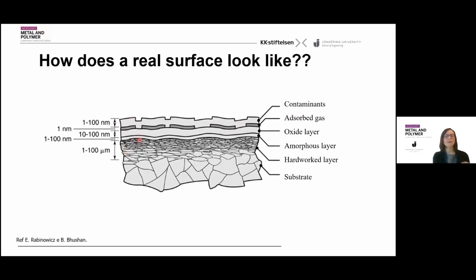We can recognize several layers. Going from the core of the component toward the surface, we see the normal composition and microstructure. Moving toward the surface, we start to see a layer of hard-worked material where the grains are smaller and full of defects. Going forward, those increased stresses transform the material into an amorphous layer, on which almost always we find an oxide layer, on which there is a combination of adsorbed gases, contaminants, oil residues, and lubrication residues from previous steps.